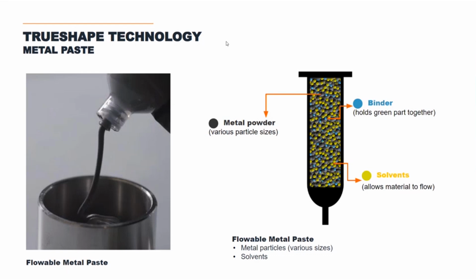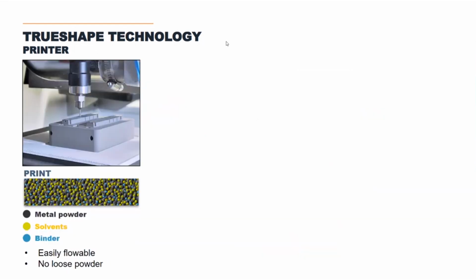So during the printing step, the material is flowing. We're not actually heating the material. It's viscous enough that we're just using a pump to push it through a nozzle like you're seeing here. There's no loose metal powder involved in this process because it's all encapsulated inside of the paste, but we're just extruding this paste material through a nozzle like you're seeing here with a pump.